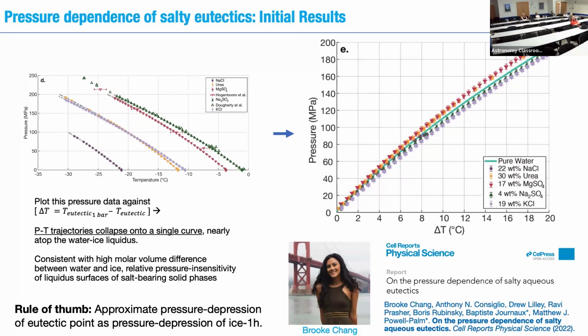And of course this jumped out to us immediately because we take these very different starting scenarios that are 25 degrees apart, and then when we plot them in terms of eutectic point depression, as opposed to just eutectic point, we see that they all collapse onto one curve. And then, not coincidentally, that curve sits perfectly atop the freezing point depression of pure water, right? So this led us to an initial rule of thumb that we could maybe, for a wide variety of salt systems in water, approximate the pressure depression of the eutectic temperature using the pressure depression of ice 1H, right? So however much you would shift the ice 1H melting point is how much you'll shift the eutectic temperature.